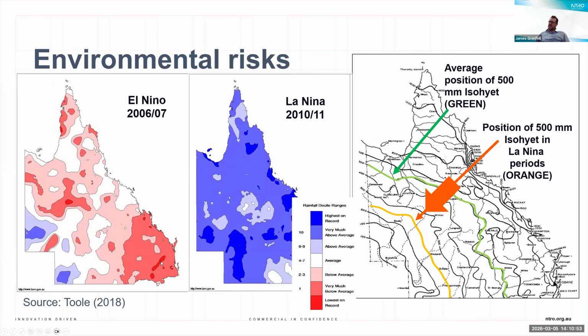And again, obviously, we're affected by weather cycles, and in Australia, we go through this continual cycle between El Niño and La Niña, where we have much drier, hotter periods and much wetter periods that we obviously have to deal with in our network. And so these weather periods are typically lasting somewhere in the region of say 5 to 10 years, where we'll have 5 or 10 years of very dry period, followed by 5 or 10 years of very wet period. And obviously that's going to have significant effects on the road network and the operation of the road network.